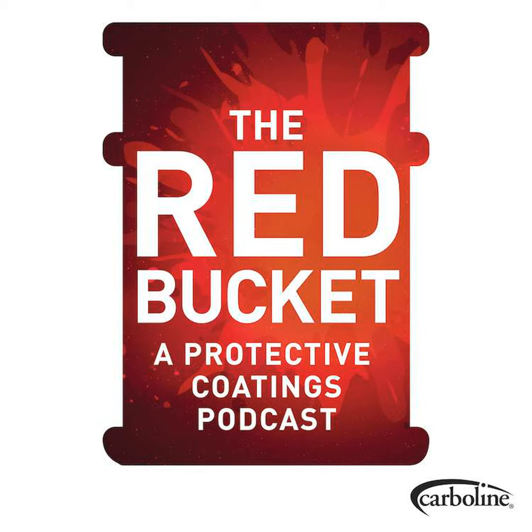And so many times in the industry and the conversations I've had, there's this idea of separating, oh, well, I don't care about color and gloss, right? I care about corrosion. And the reality is they're not separate. If gloss is starting to drop, you're actually starting to see that coating film break down at the molecular level. Again, you can't really see the bonds breaking, but the effect of that is that you're getting micro cracks and voids within that coating film. And what does that do? Well, it allows moisture and salt, and then over time, UV light to get down to that mid coat, which in a lot of cases is an epoxy.